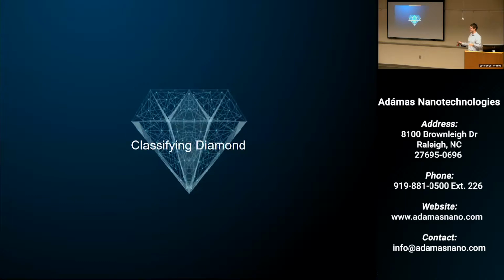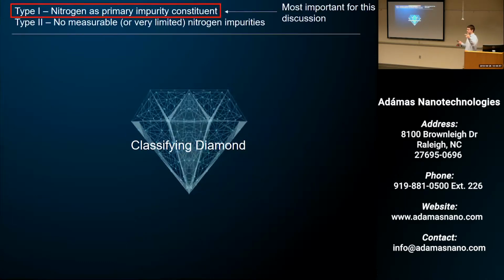I think it's important first to give a general classification of diamond. There's generally two types of diamond, type 1 and type 2. Type 1 diamond is notable for having nitrogen impurities as its primary impurity constituent. And as you will soon see, the nitrogen is the most important player in this game of color centers in diamond. Type 2 diamond, which I won't really discuss, contains almost no nitrogen impurities.